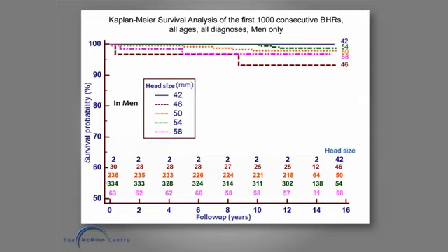However, when the head size is small, then by cup malposition, in small sizes you get onto edge loading and edge wear quicker. So you have to be all the more accurate in your implantation with small sizes. And I think I'm reasonably good on component orientation, and that's why my series, unlike a number of other series, show no relationship between head size and failure.